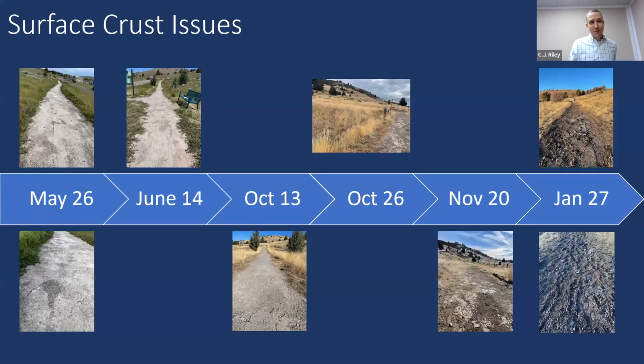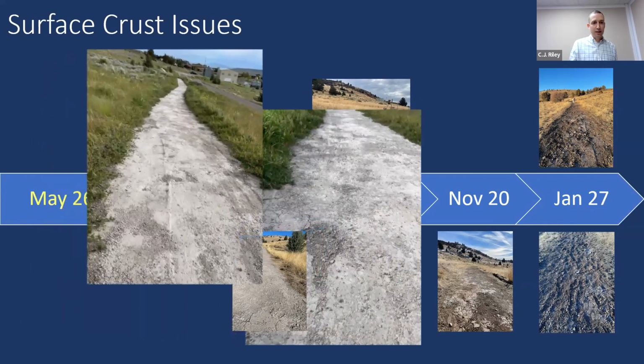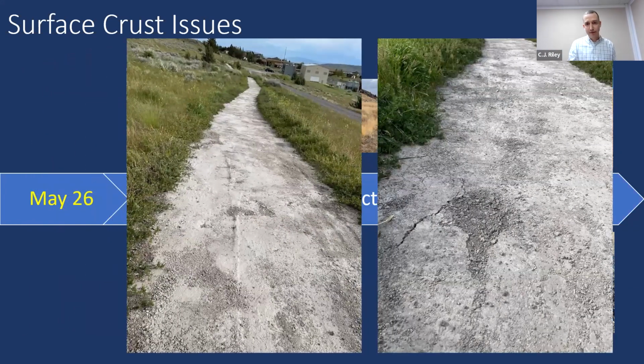But all of the things that were positive about this trail really started to degrade. And I want to show you a timeline that shows us what happens over the course of about 6 months, 7 months with this project. So these are less than a month after implementation. And you can see here on the left photo that we've got a relatively smooth, consistent surface. And that was true in a lot of places along the trail. There were other places where, again, you can see the aggregate is exposed, it looks looser, and there were spots where the material simply wasn't bound as well as it could have been.